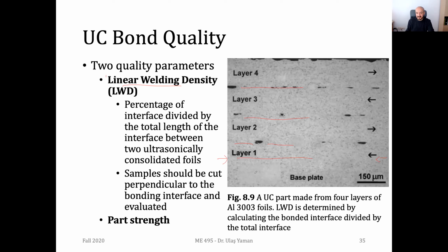At the interface between the base plate and the layer, we don't have any openings, as you see. But if you look at, for instance, the interface between layer 1 and layer 2, we have some impurities, we have disconnected regions, and you can compare the percentage of these regions with respect to the length of this cross section. And by using that, we can obtain easily the linear welding density. Obviously, it's 100% for the interface between the first layer and the base, but it's less in the upcoming layers. Actually, it's the least between the third and the fourth layers. Maybe around 60% or 65%, I don't know.